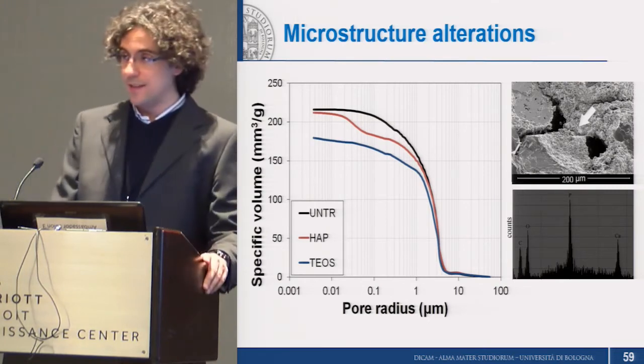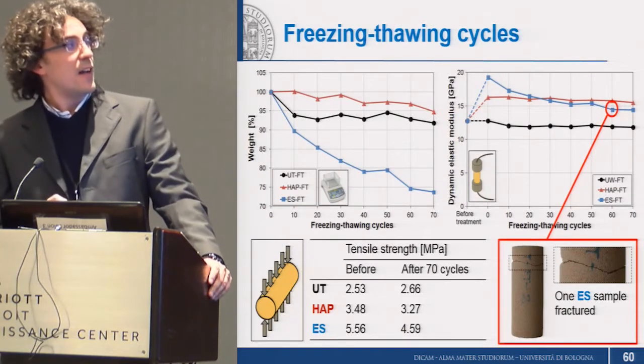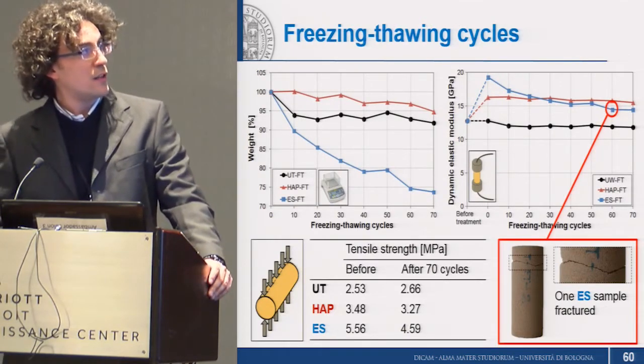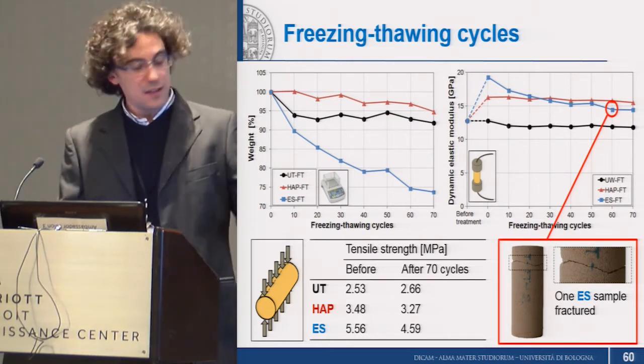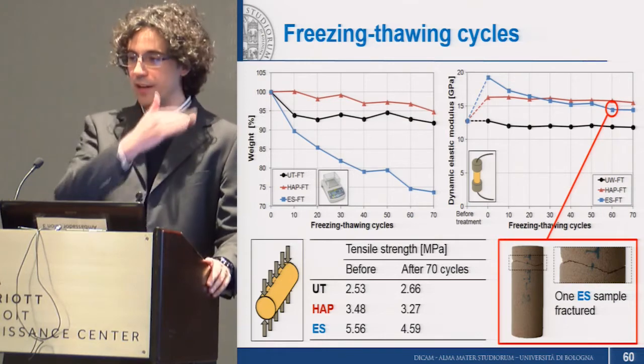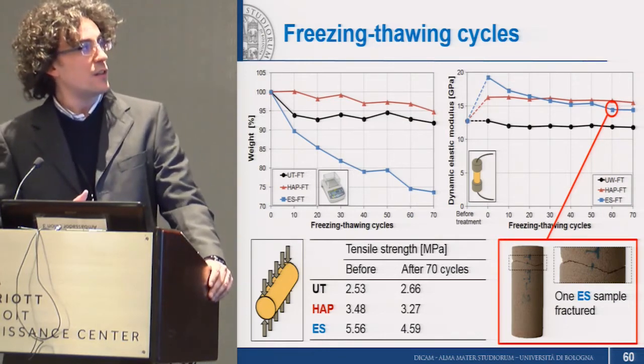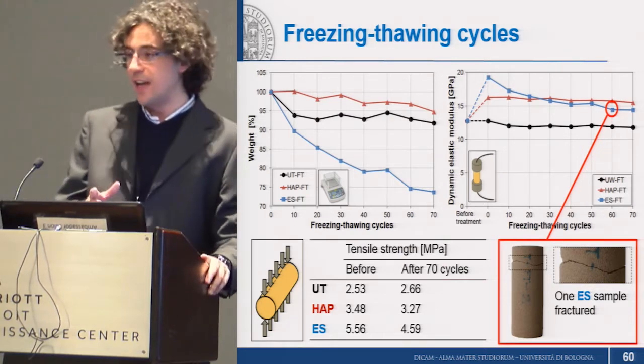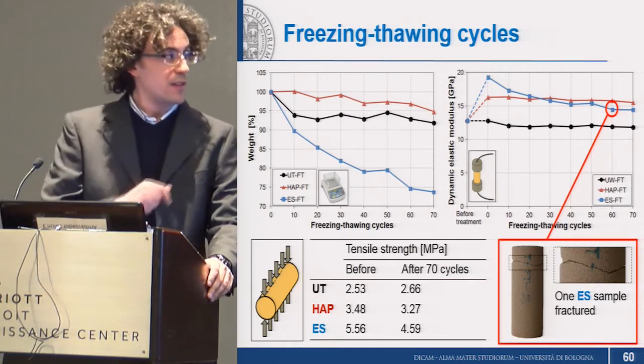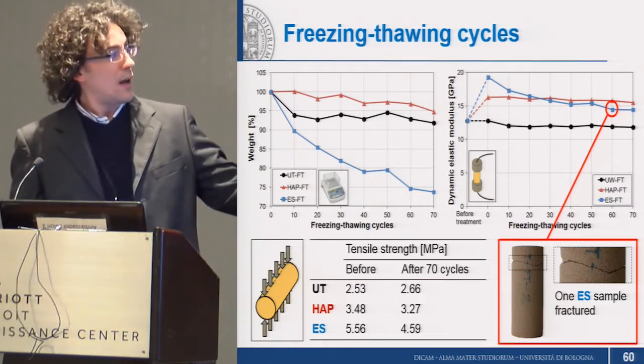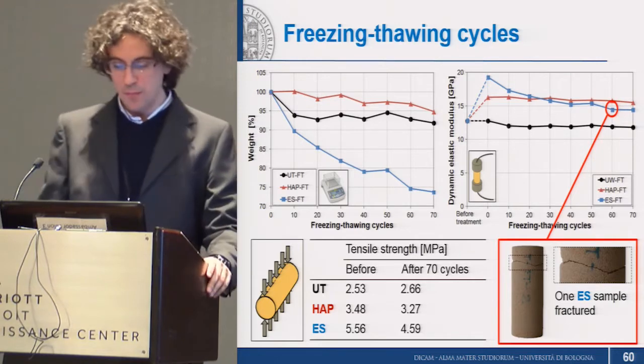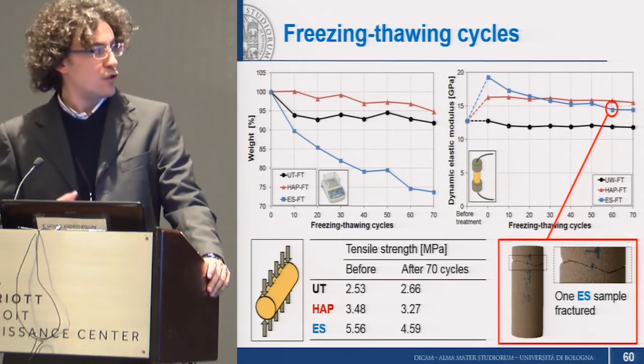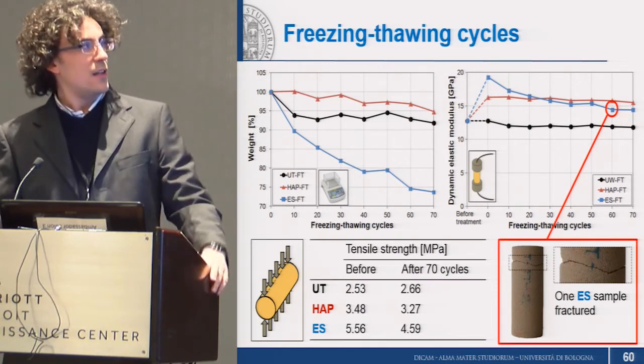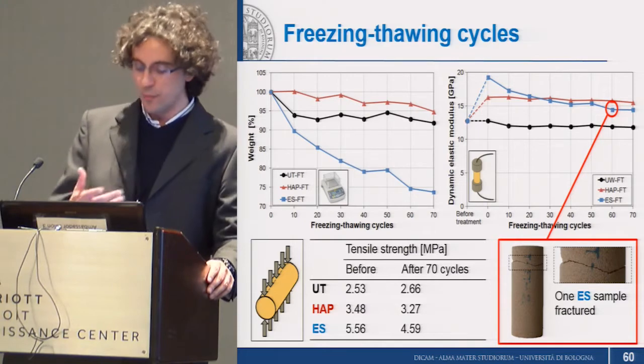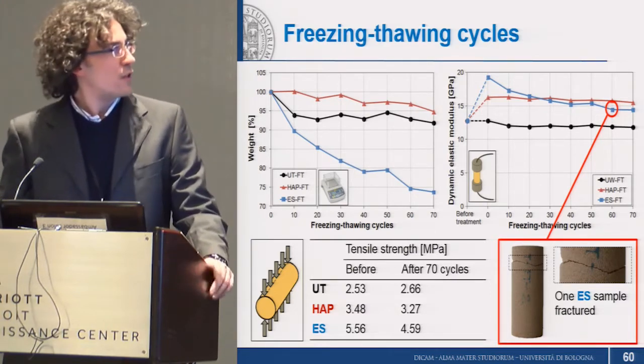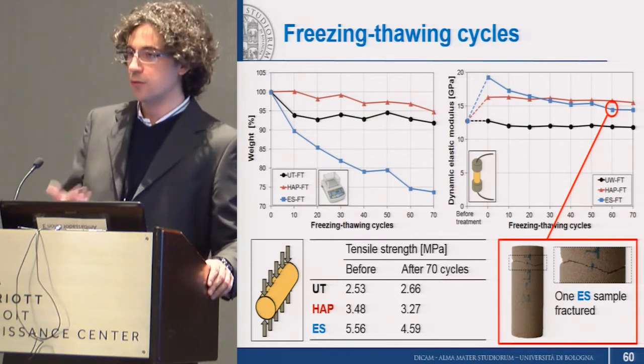So we first started testing the effect in terms of durability to freezing-thawing cycles, and we found that, in spite of the initial benefit of using ethyl silicate for consolidation, over time there was a decrease in mechanical properties after consolidation with this alternative treatment. And actually the only sample that failed, so it fractured spontaneously, was a sample treated by this alternative consolidant, while our consolidant in red basically remained stable over the cycles, which is positive. So from this, we got an indication that the alterations in pore size distribution by our treatment are not so negative. And fortunately, we also found a confirmation in terms of resistance to salt crystallization.